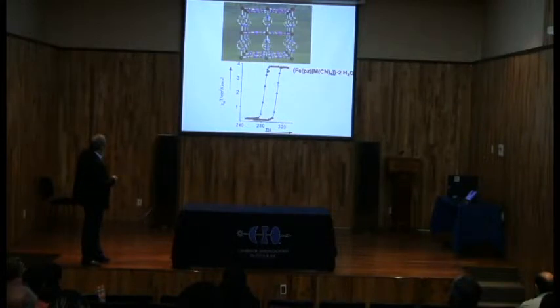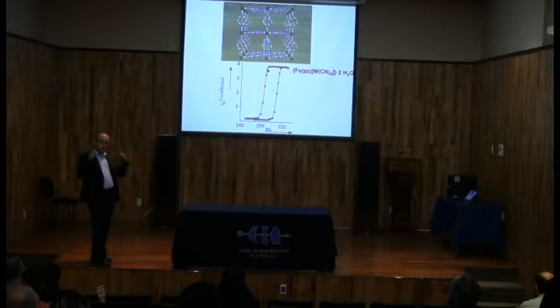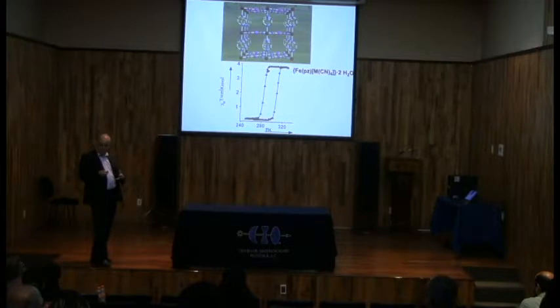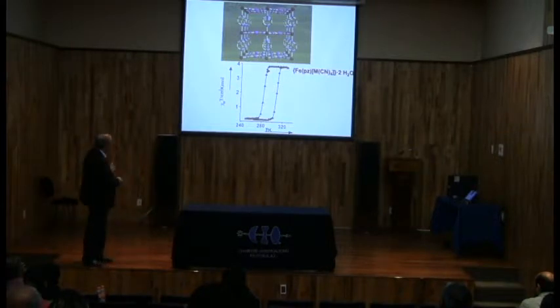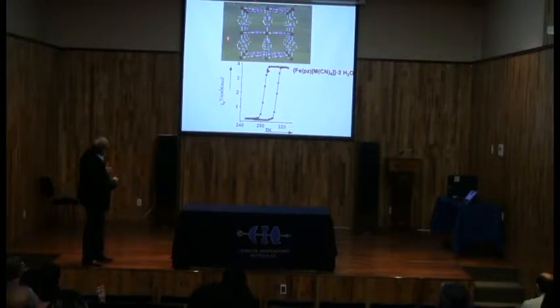Of course, we are interested in cooperative systems where the interactions between molecules are strong enough, so that we have the hysteresis loop, and where the crossover is at room temperature. If you look at this coordination polymer system, you have the iron here, and nitrogen, carbon, nickel, carbon, nitrogen, and iron. It's a polymeric, 2D system.